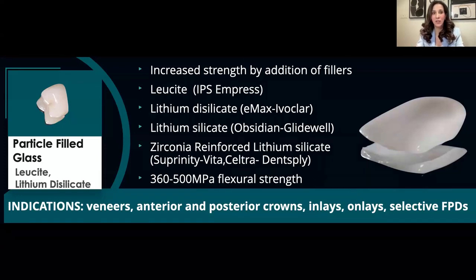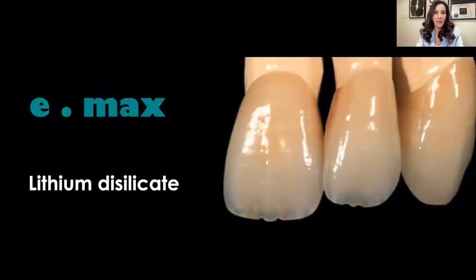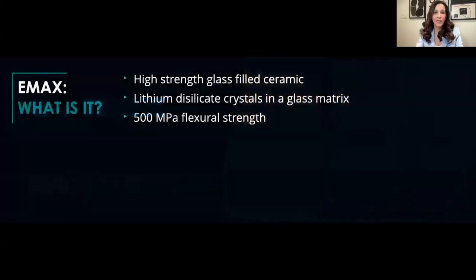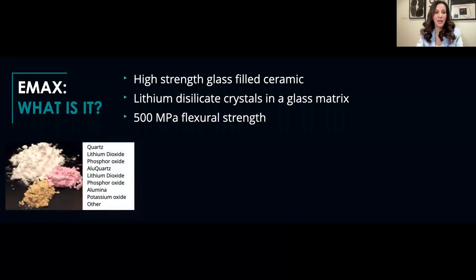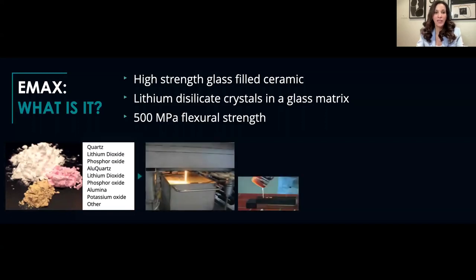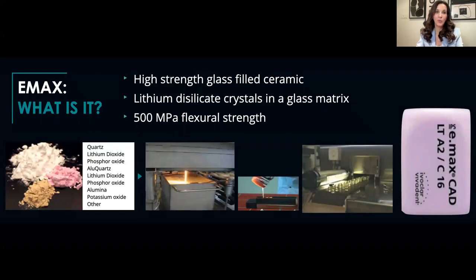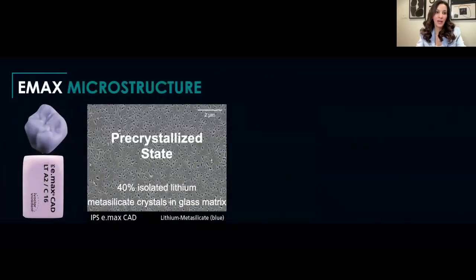And if I can just zone in on the lithium disilicate material or Emax, this is a material that I use mostly in my practice, and it is comprised of lithium disilicate crystals in a glassy matrix. And the material, as I said before, is much stronger than our feldspathic, and it's stronger than the particle-filled glass materials as well. And it consists of a number of materials that you can see up on your screen that are all combined together and formulated in these blue blocks, which is the pre-crystallized state of the material. And in this blue phase, or the pre-crystallized state, you have 40% isolated lithium metasilicate crystals in a glassy matrix.